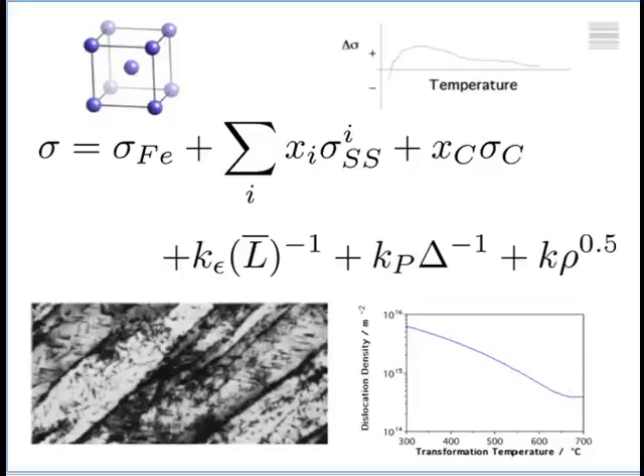This is the crystal structure of ferrite. We have an iron atom in the middle and a layer of iron atoms at the top and at the bottom. Now clearly, when this layer moves over the underlying layer, it will have to go over some bumps. And that means if you have pure iron, absolutely pure iron, without any structure, that means no grain boundaries, without any alloying additions, that will still have some strength because the atoms will have to slide over the layers underneath. And that is the strength of pure iron.